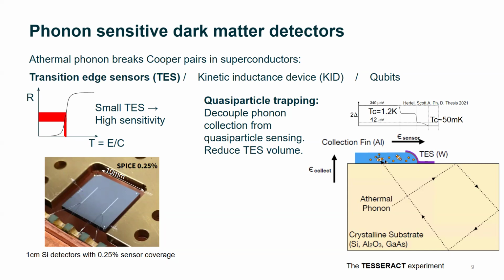So the idea is after the phonon breaks Cooper pairs and creates quasi-particles, they start at this higher energy level because of the higher Tc of the aluminum. Then it thermally diffuses, and once it reaches this region where it overlaps, it has the proximity effect. The Tc slowly drops to the Tc of the tungsten, which is around 50 millikelvin. So in this dropping process, the quasi-particles lose energy and won't come back. So all the quasi-particles created in the aluminum will eventually be trapped into the tungsten. And in this way, we can concentrate our signal in a smaller volume that drastically increases our sensitivity and lowers the energy threshold. Okay, so this is the state of art for TESs.